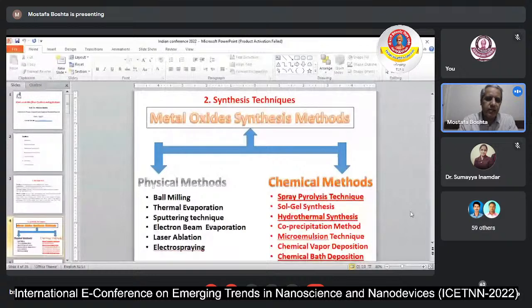Spray pyrolysis, as everybody knows, is a simple technique. We use an aqueous solution with pressurized air to atomize and spray the solution into fine droplets which fall on the surface of the hot substrate. This substrate is heated by a furnace or hot plate, and the spray droplets continue on the surface to complete the thin layer or thin film according to the conditions, which we can optimize for each material, each thickness we need, and each application.